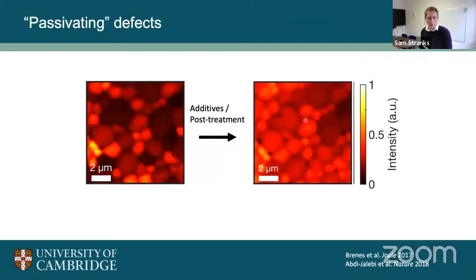And so, speaking of improvements, this is some work where we are trying to improve these, and we're looking at different additives and post-treatments of the films when we make them to produce a better luminescence map. You can see on the left before and after these treatments, it's much more uniform. It's much more luminescent as well, which is what we're seeing in the color here. So this is improving things and removing some of these problematic traps and defects.